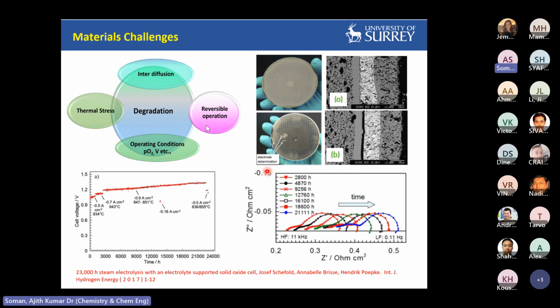Maybe the rest of the things are mostly optimized by many of the researchers. So we will be seriously looking at this problem. So we will be doing the electrochemical impedance. If you look at the long-term operation, like 2000 to 20,000, you could see the increasing impedance arc, so that the overall resistance is getting higher because of the delamination of the material from the surface.